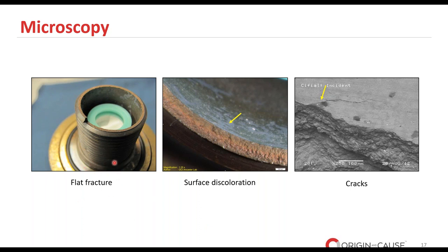First off, we have this flat fracture surface, and this is a characteristic of certain types of SCC. A flat fracture might suggest that there was little to no deformation of the material before it fractures. You can think of this like pulling apart licorice or putty. It stretches a significant amount before it breaks. And at the center or the focal point, the fracture will be thinner than the rest of the licorice stick. Whereas in our case, this faucet, it looks more like we broke apart an ice cube or a piece of glass. It didn't stretch.